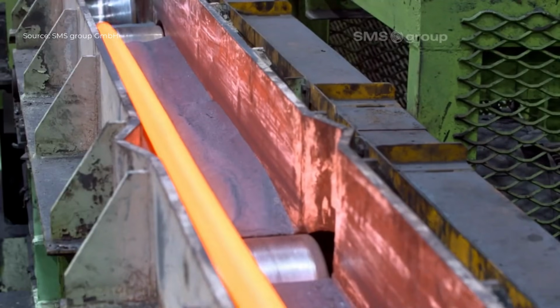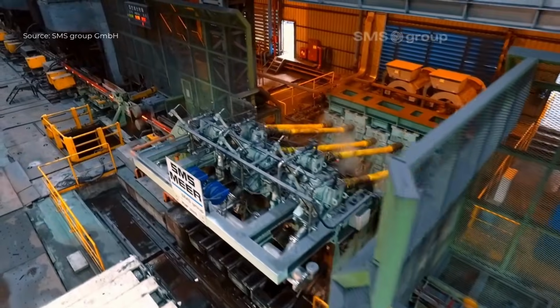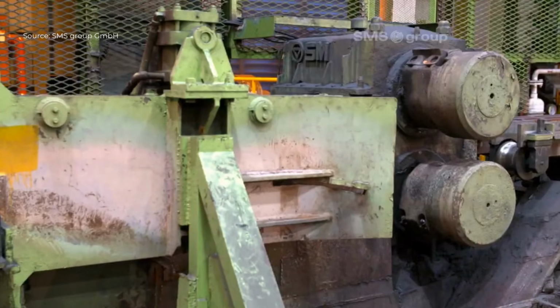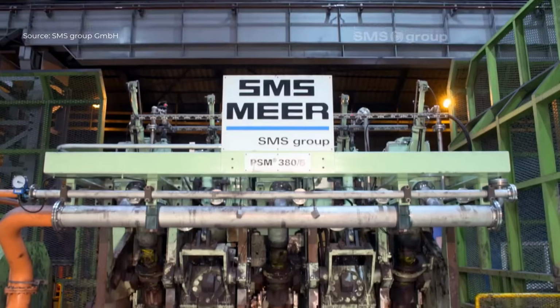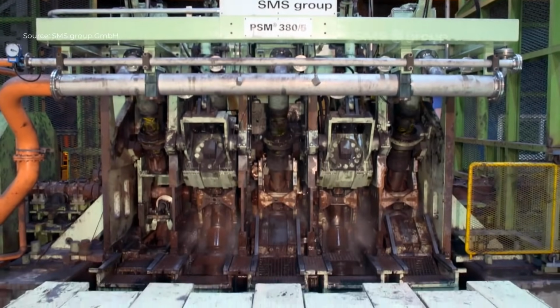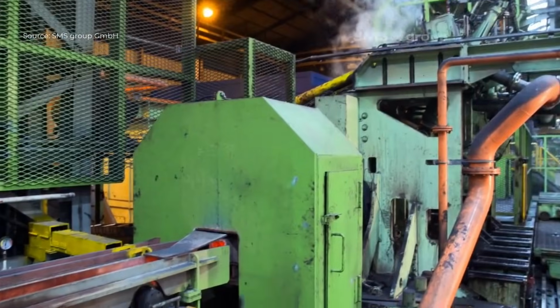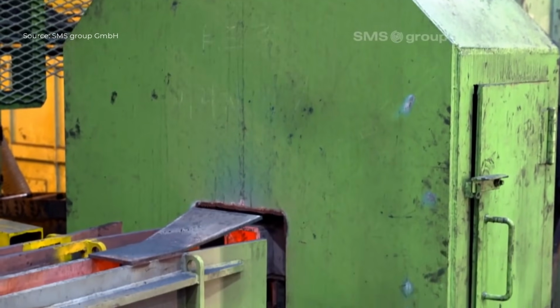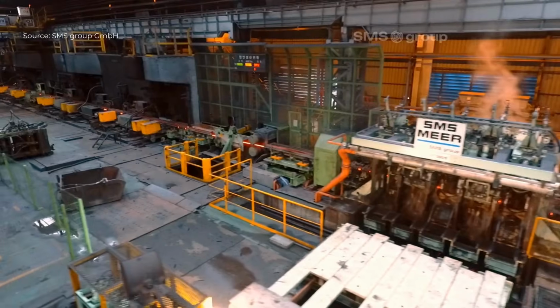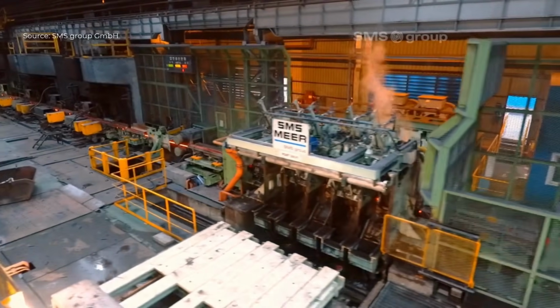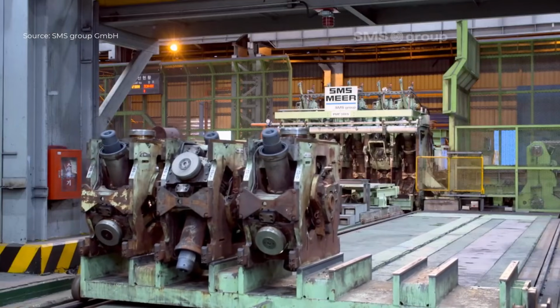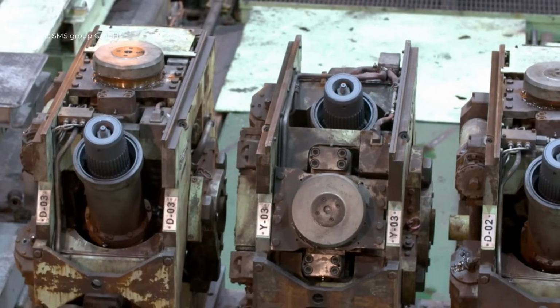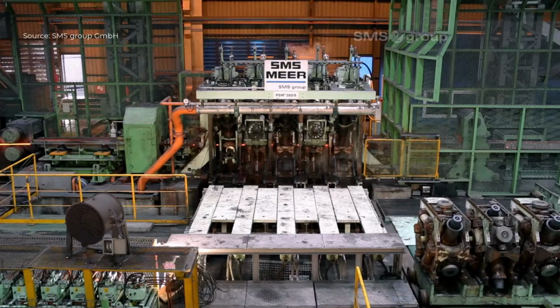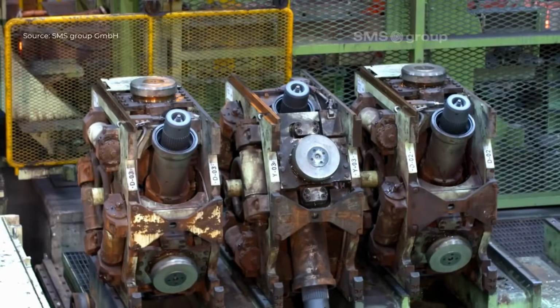The PSM is dedicated to rolling special bar quality steels in final diameters ranging from 25 to 83 millimeters. Diameter tolerances achieved in this process are 6 to 10 times tighter than standard requirements and remain consistent along the full bar length. Rolling can also be performed in free size mode, allowing any required intermediate dimension to be produced. This capability helps minimize machining allowances for downstream processes such as peeling.